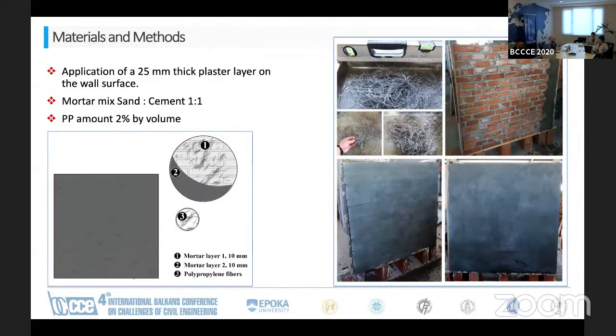Before doing the diagonal compression test, the strengthening technique of polypropylene fibers that are embedded in this inorganic mortar coating is shown in the figure here. So basically, these are the polypropylene fibers, which are pretty thin, and we have cut them into 12 millimeter length. They are inserted in the mortar mix. They are dry mixed together with sand and cement. And then afterwards, the mortar is prepared and applied. One layer is applied firstly in order to improve rotation. And then we are adding the second layer. So the overall strengthening plastering layer is about 25 millimeter thickness.